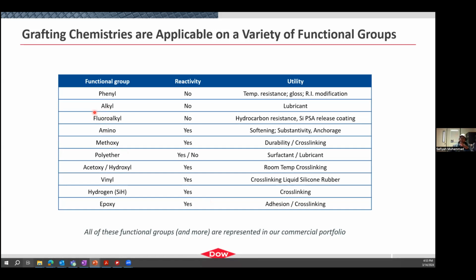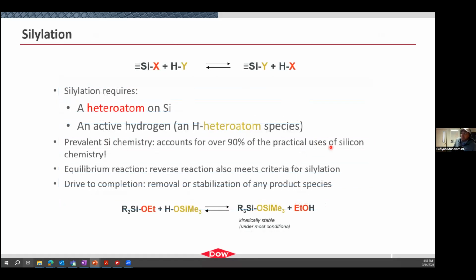Now you'll notice that some of these groups say no reactivity next to them. That is just an R group switching out for an R group, and you are not expecting any reactivity on that group. But there are some groups that we install on our silicone materials that are reactive, and we want them to be reactive and perform what we call silylation chemistry. Those groups are represented here in bold, and we often use them for cross-linking, in order to make PDMS curable and more stable, right? The process to get a cure on your silicone polymer is through a process called silylation.